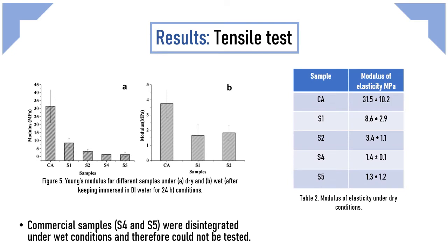Tensile tests measure the force required to break a sample specimen and the extent to which the specimen stretches or elongates to that breaking point. As we can observe in figure 5, there is a significant difference between the elastic modulus of electrospun CA-based nanofibers and commercial samples. Under dry condition, for S1, S2, S4, and S5, the modulus was much lower than CA nanofibers. In general, these results show that mechanical strength of pure CA nanofibers was more than any other commercially available samples.